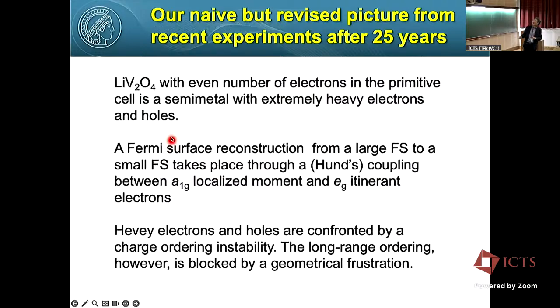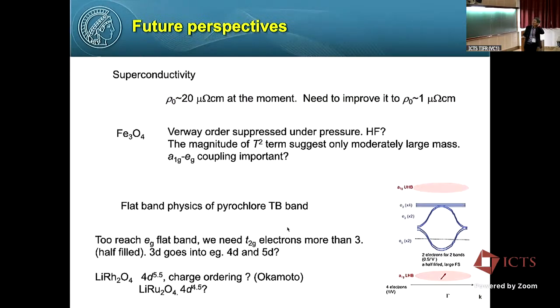And lithium vanadate is a semi-metal, with an electron mass of maybe 200 to 300. And we have both electron and hole, and that was produced by coupling between local A1G and itinerant Eg. And this part I don't know, but according to my theory colleague, the coupling comes from Hund's coupling. So that's quite different from Kondo. And those heavy electron and holes are confronted by charge ordering instability. But long range ordering is blocked by geometrical frustration. That's maybe my future perspective, and I will finish my talk. Thank you very much for your attention.